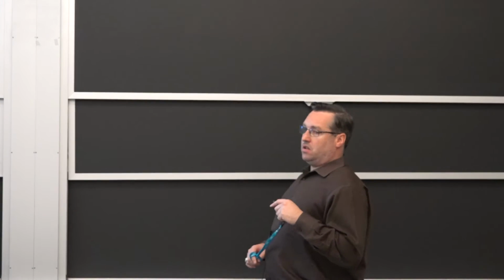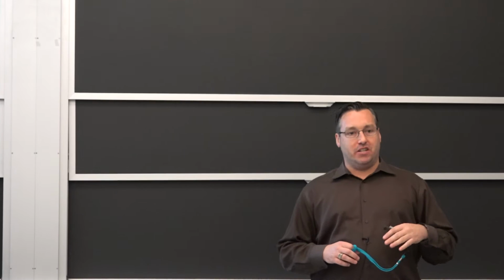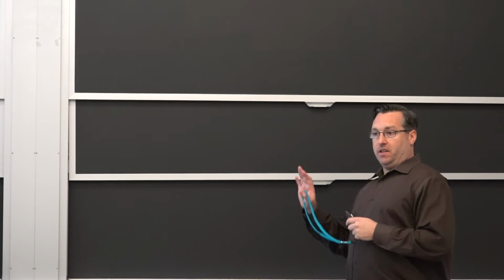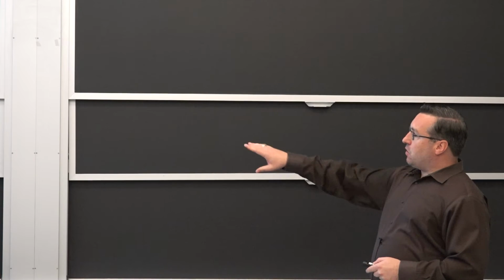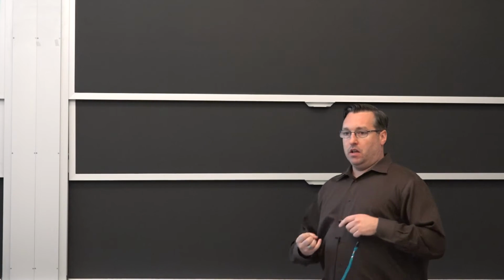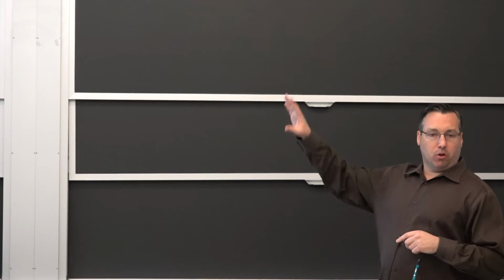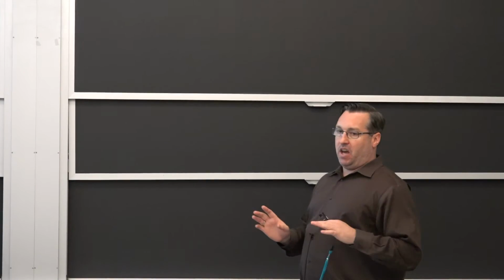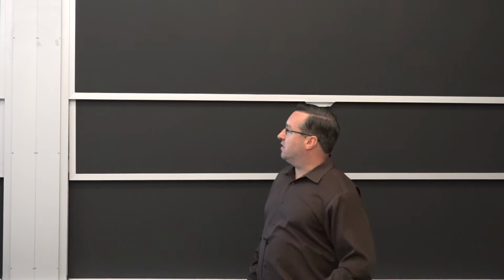One of the things Professor Egan and I discussed the other day was the billion tons per year club, and this is a class on structural materials. Float glass in and of itself is about 53 million tons per year produced. That's on the same range as aluminum alloys. We're still nowhere near steel, right? Steel's like 1.5 billion, whereas this is only 0.05. But this is only float glass. It doesn't take into account glass for recycling and bottles and solar panels and other applications. If you take all glass applications and put them together, we're probably talking about 150 million tons per year. So we're not talking billions, but it's still a significant amount.